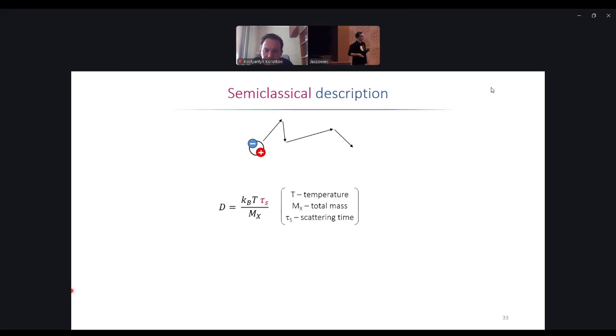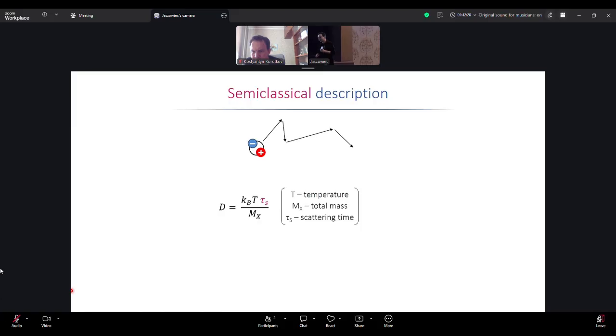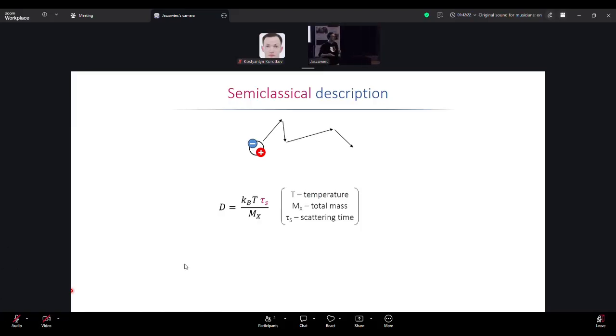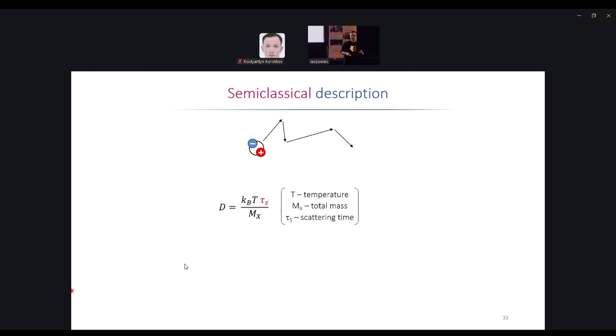With coherent spectroscopy. Coherent spectroscopy, depending how you do it, is not trivial. Luckily, people do it, like 2D Fourier spectroscopy, four-wave mixing. There you can get a dephasing rate. If you don't have access to it, and you have a good sample, how can you estimate the dephasing rate without doing coherent spectroscopy? And those doing coherent spectroscopy, please close your ears, because it will be a bit heretical. But in practice, it can work. How can you estimate dephasing if you don't do coherent spectroscopy? To say something reasonable about it.